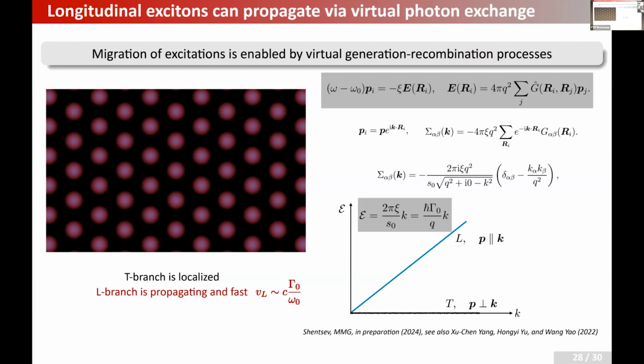I have just one last question. These are optically excited excitons for the transport setup that you study. I guess the Förster channel is turned off if the excitons are in equilibrium, right? If I use gating to create the electron-hole layers rather than generating them by photons. It's a good point. If we discuss the homogeneous system, then of course there will be no diffusion. There is no direction for excitons to travel. Also, if you create, say, optically forbidden excitons, the excitons with zero radiative decay rate, say spin-forbidden excitons, then the situation will of course be different, and this mechanism will not work.